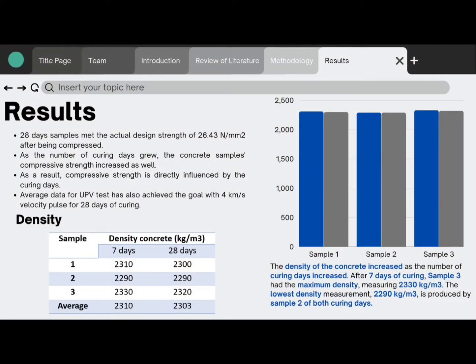One of the 28-day samples reached the actual design strength, which is 26.43 Newton per millimeter square after being compressed. This is because as the number of curing days grew, the concrete compressive strength also increased. Also, for the UPV test, the average data achieved was a pulse velocity of 4 km per second for the 28 days of curing.